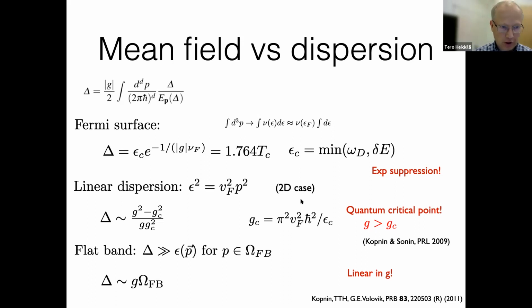Now you can consider the case of graphene, which has a linear dispersion, especially the 2D case. What one finds by plugging this dispersion into the self-consistency equation is that delta becomes even smaller. The Cooper instability doesn't work anymore, and you actually need a finite interaction in order to get any delta, because of what is called a quantum critical point. I will show in a moment how large this interaction needs to be, but basically there is a specific value for it.